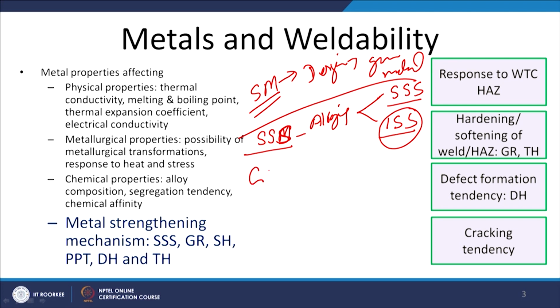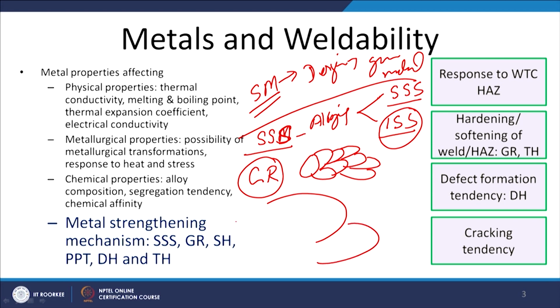In case of those which are refined using the grain refinement principle, this principle is very simple, where reduction in the grain size of the metal leads to an increase in the yield strength as compared to metals having larger grain sizes. So, greater is the grain size, lower will be the yield strength as per the Hall-Petch relationship. Those metal systems designed to be strengthened through grain refinement have yield strength inversely proportional to the grain diameter. Larger the grain size, lower will be the yield strength of the material. So, this is another approach of strengthening of the metal system.